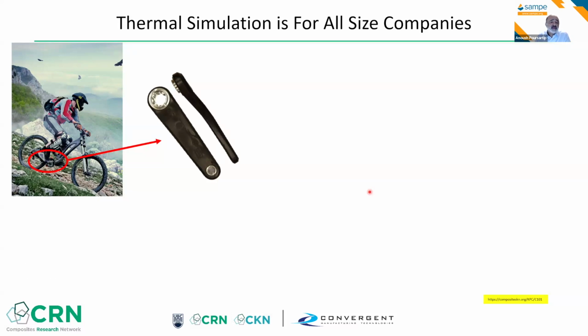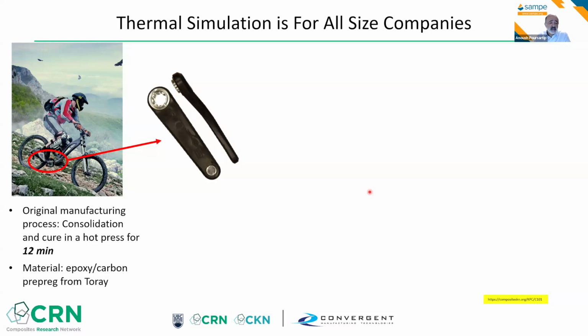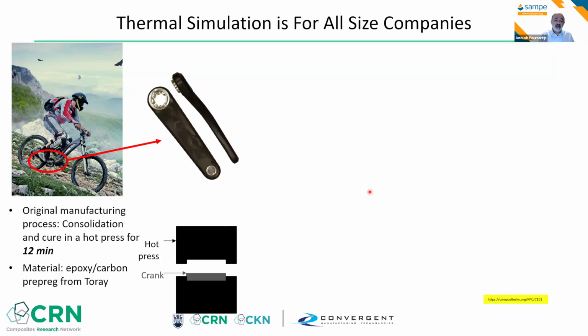So the way they make these cranks is that they consolidate and cure them in a hot press. It's a carbon epoxy prepreg from Toray, and their standard cycle was 12 minutes. They wanted double production. The press was their bottleneck because the crank spending 12 minutes there, that was their most expensive piece of equipment in the factory. They could not afford to basically put in a new press facility.